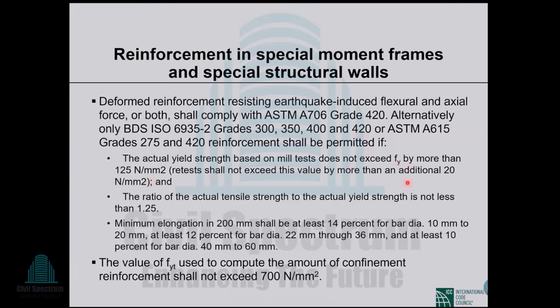Fy cannot be more than 125 megapascal above the specified value. The ratio of the actual tensile strength to the actual yield strength is not less than 1.25. That is ductility class D. We have shown that in BDS also there are 4 ductility classes. The TY ratio defines those ductility classes. If the TY ratio, that is ultimate strength or tensile strength divided by yield strength, is 1.25, that represents ductility class D. So we have to use, say, BDS ISO 6935 420D WR bar. That is important. Minimum elongation in 200 millimeter shall be at least 14% for bar dia 10 millimeter to 20 millimeter.